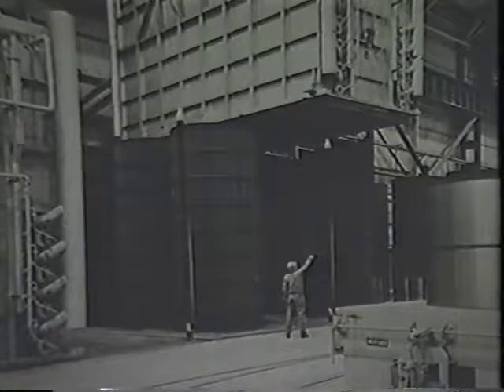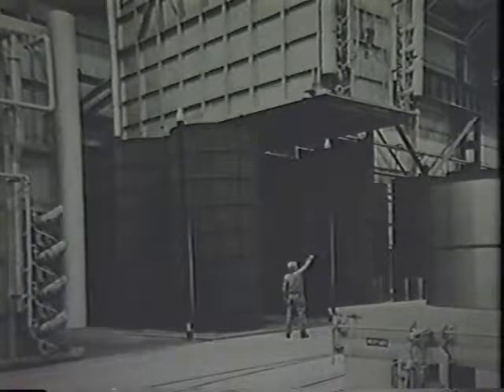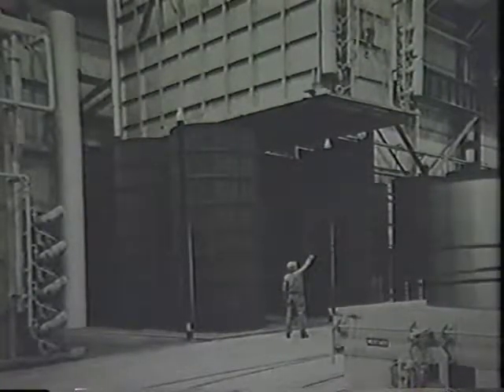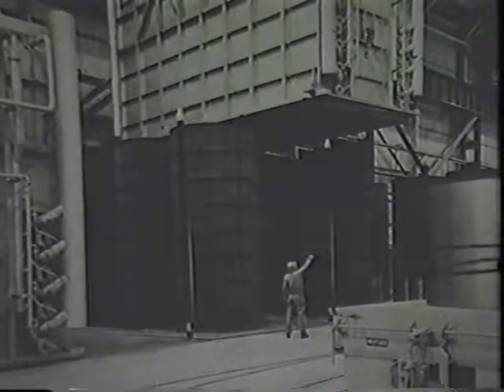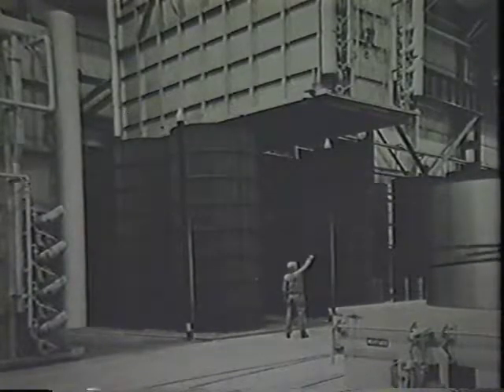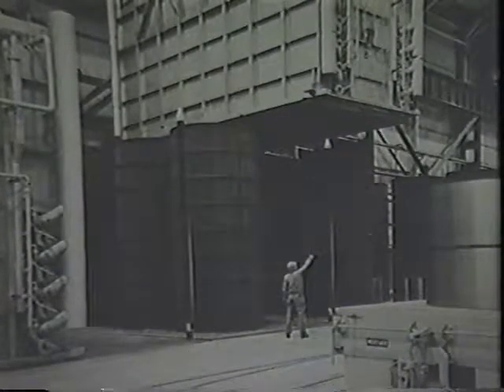Around that stack of coils, whether it be 2 high, 3 high, or 4 high, we put what's called an inner cover around it. And here's that grain silo looking device. Okay? Underneath this inner cover here is the stack of coils. Got the stack, we'll put the inner cover over it and seal the bottom. We'll then exchange the atmosphere, the air, for a hydrogen-nitrogen mix. The inner cover protects the coil with that atmosphere. We get the air out and put the hydrogen-nitrogen mix in because we're going to elevate the temperature of the coil. If we don't have the proper atmosphere surrounding the coils, you're going to oxidize the strip surface, just like you did slabs in the furnace, coils in the hot mill. Bring it up to temperature here. If it's a non-protective atmosphere, we're going to get stains, we're going to get oxide, it's going to look blue, it's going to be unacceptable. Okay? So we have to protect the coils with a protective atmosphere.